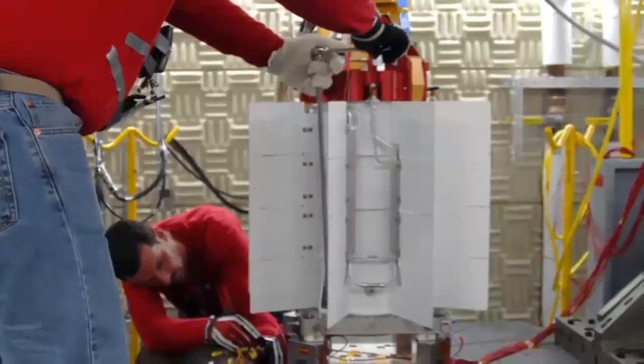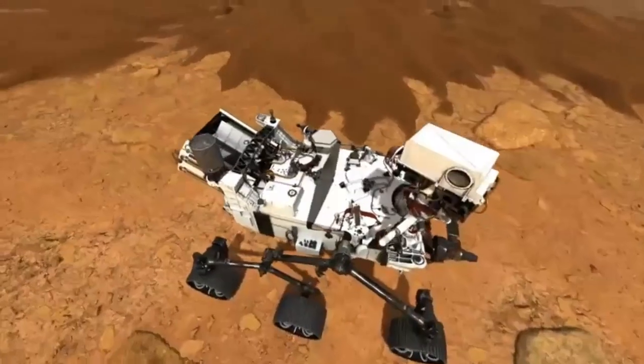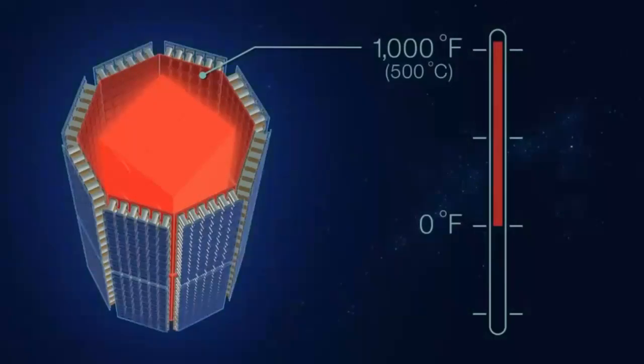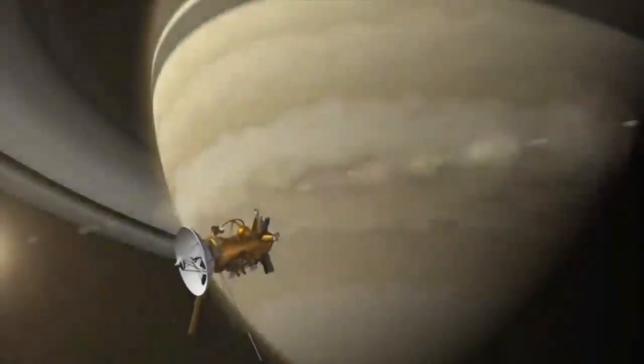Building on our results from Phase 1, we believe there is much more potential to unlock here. Using low bandgap materials such as InAsSb and nanostructured arrays to limit potential loss mechanisms, a 25x improvement in mass-specific power and a 4 order of magnitude decrease in volume from an MMRTG is an early estimate, with higher performance possible depending on operating conditions. TRC technology will allow a proliferation of small versatile spacecraft with power requirements not met by photovoltaic arrays or bulky, inefficient MMRTG systems. This will directly enable small satellite missions to the outer planets as well as operations in permanent shadow, such as polar lunar craters.